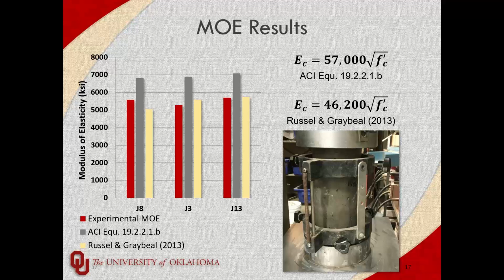that's pretty typical when you start looking at higher strength concretes, is that the relationships between them become a little less exaggerated, in that you don't always get 10% tension strength out of a UHPC at a higher strength than you would in a normal weight concrete, which would be really awesome if you get 10% of 22 KSI for tension strength, but unfortunately that's not the case.